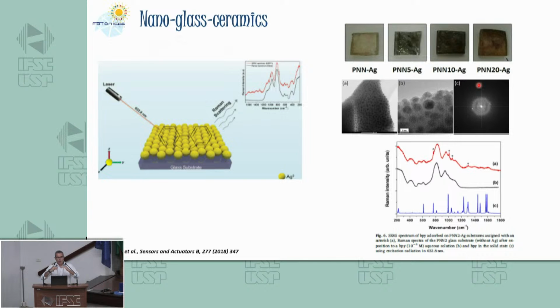And so when you have a surface like this one, with the nanoparticles on the surface of the glass, the organic compound, for example, can be attached to this surface, and then the Raman signal will be increased. And sometimes it can be increased 10 to the 5 times. So the detection will be much better. And Raman is a very nice and easy methodology to study these materials, to verify the existence of a very, very small quantity of, for example, in this case here, we show that the surface could be used to detect some medicines.